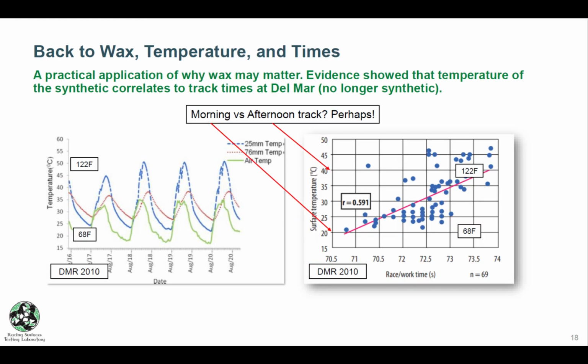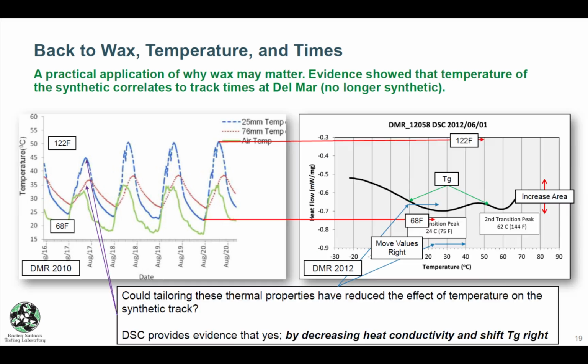So looking back at the surface temperature versus the race times, we actually do have strong evidence that really does support this, and we can show that you're probably going to have a difference between the morning track versus an afternoon track. And so could we have tailored these thermal properties to reduce such an effect?